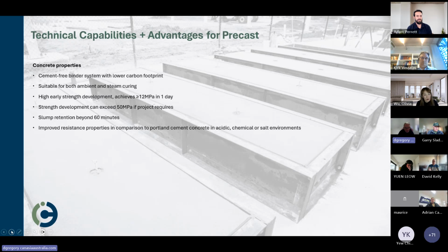We can achieve very high early strength development. We recommend over 12 MPa in one day. And Kirk will touch on the reasons why we probably need slightly lower one-day strength than traditional cement-based concrete. It's due to the bond strength between our geopolymer concrete and the reinforcement steel in the system. We have a much stronger bond strength. And we've demonstrated this by lifting 3 metric ton beams with a one-day strength of 12 MPa within 24 hours.